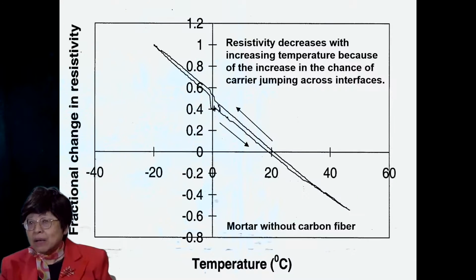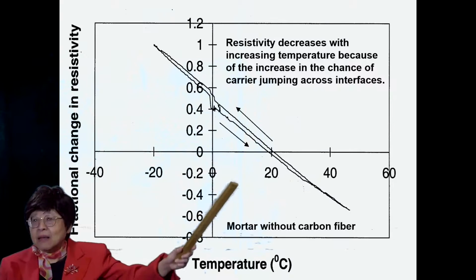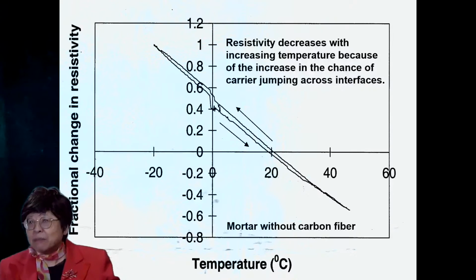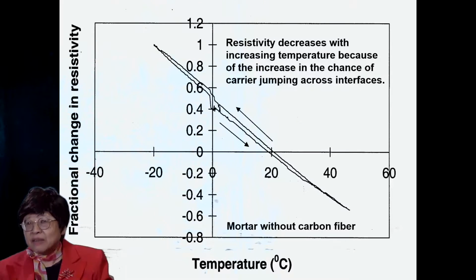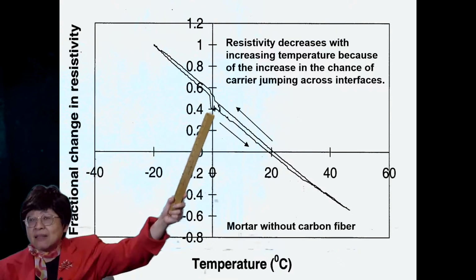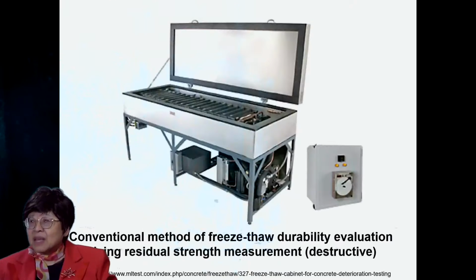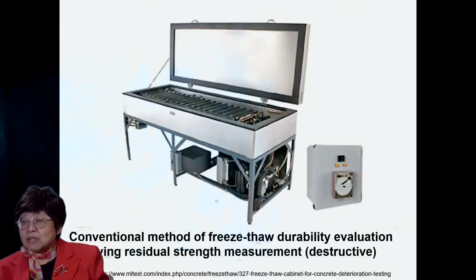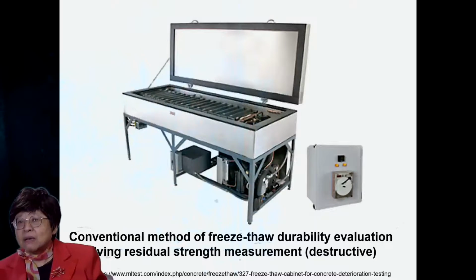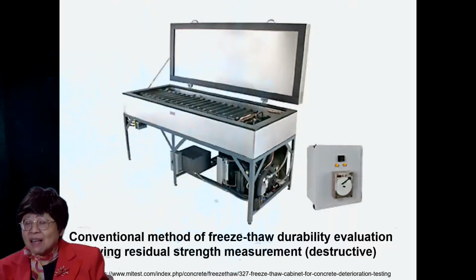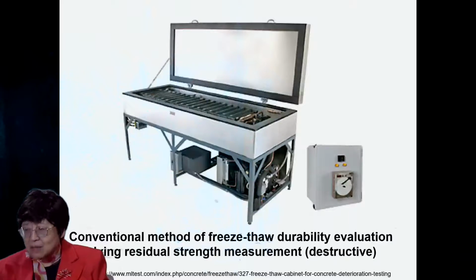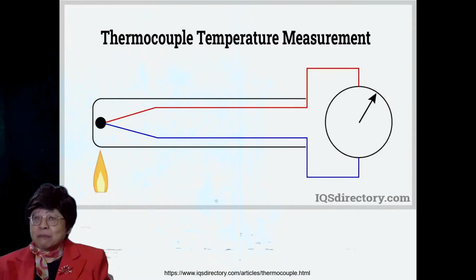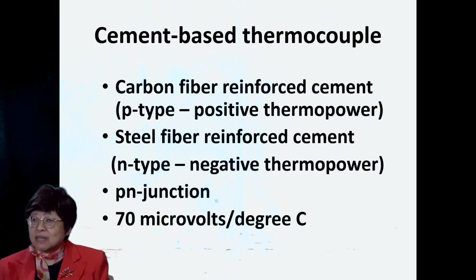Now, note that this is the plot of the resistivity versus the temperature, and as I said, that's the trend. The higher the temperature, the lower is the resistivity. But note that there's a little glitch that occurs at 0 degrees C. This is the conventional method of freeze-thaw durability evaluation involving residual strength measurement, and that is destructive and involving many specimens, not just one.